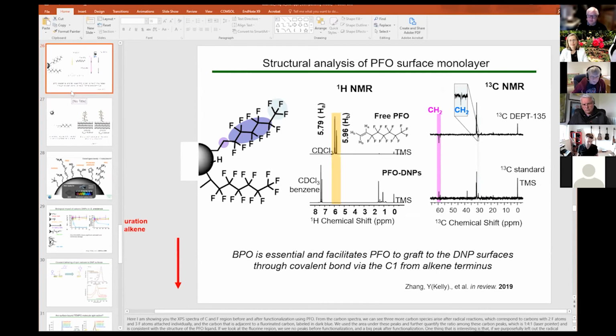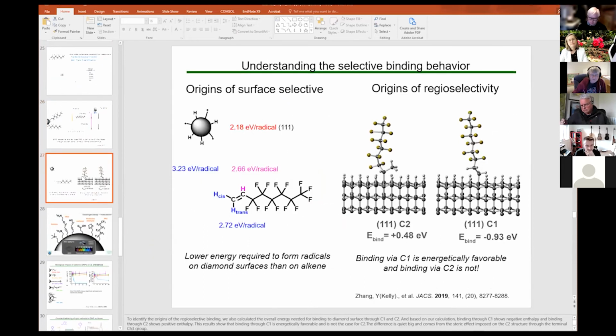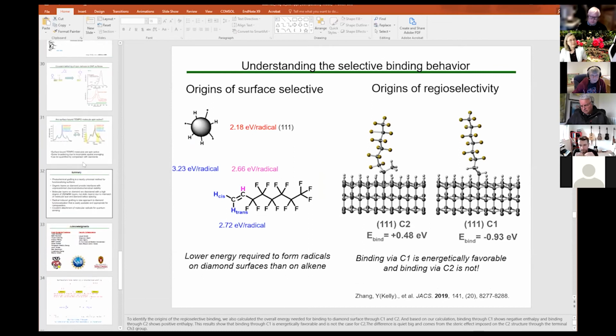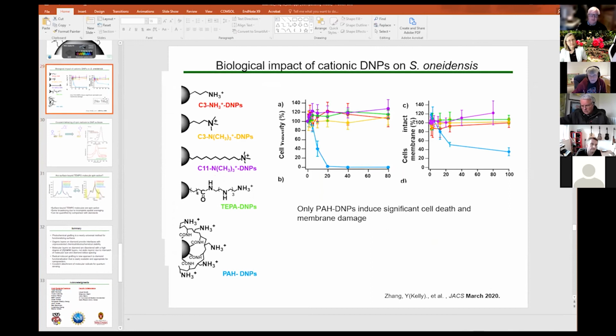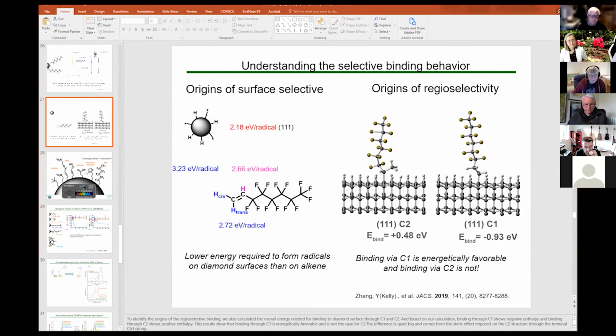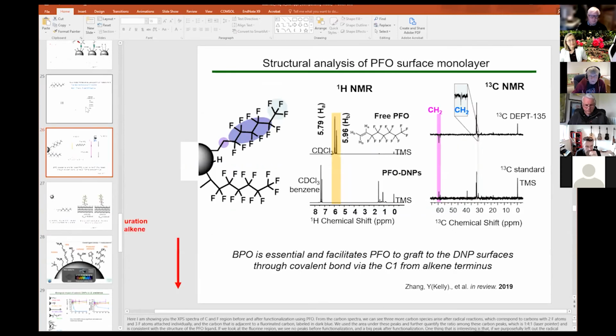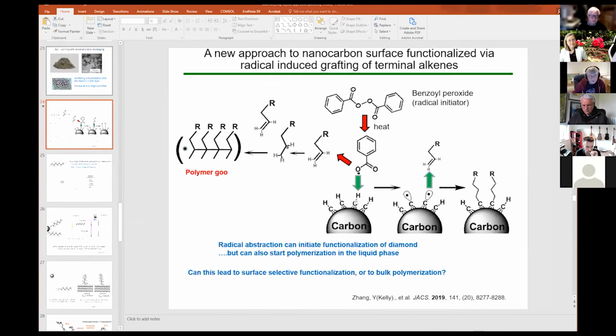The photochemical method works as long as you have a small amount and you simply disperse it in the bottom of a petri dish, so that light can actually access all of it. But that's not very scalable. This method of using the radical chemistry is actually far more scalable. In these biological studies, we need pretty decent amounts of nanodiamond, often hundreds of milligrams. For that, this radical based grafting that I started showing back here works really well. Did that answer your question?